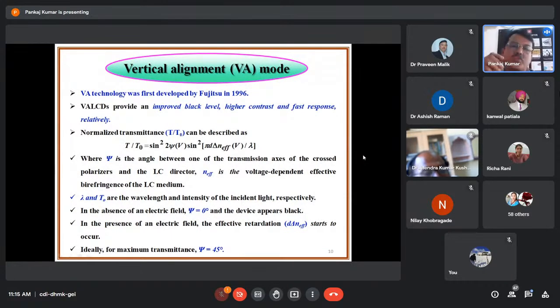When there is a 45 degree angle between the liquid crystal molecules and one of the axes of the analyzer or polarizer, then the maximum transmittance will be there. So in case of the vertical alignment, to get the maximum transmittance, we have to make the arrangements in such a way that psi should be 0 when we want the perfectly black state, and psi should be 45 degrees when we want the maximum transmittance.